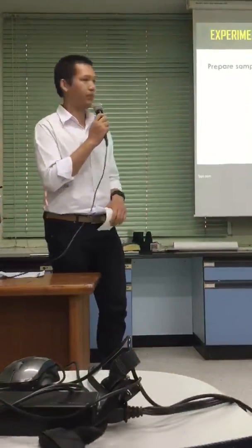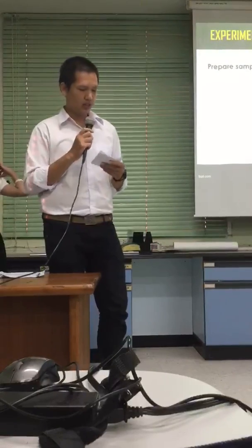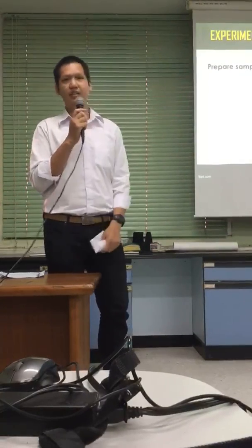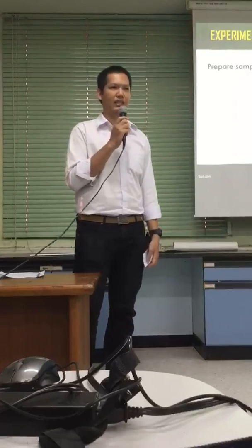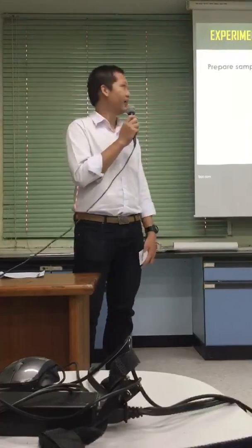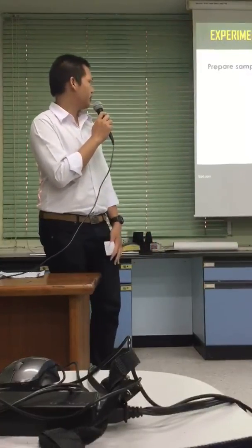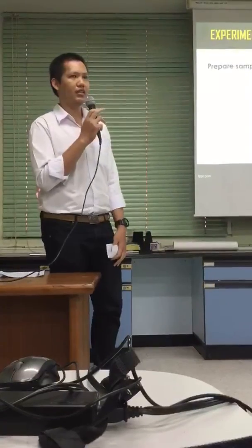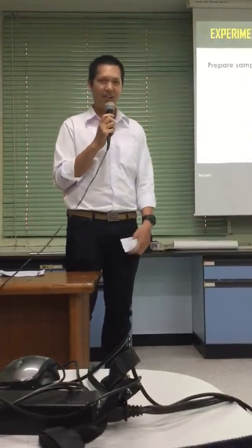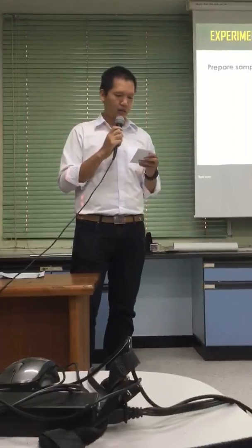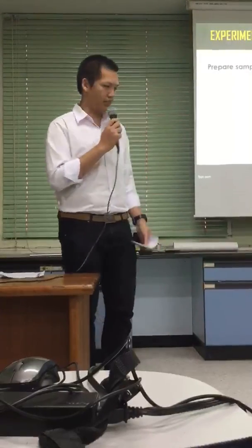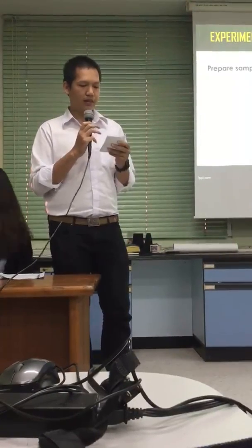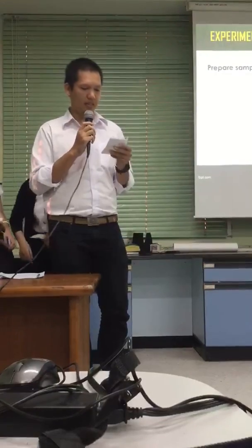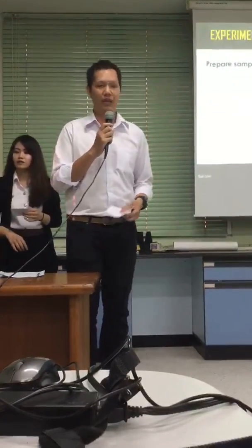In the experimental, we have two parts. The first part is preparation of sample. Then it is deposited on glass substrate by dip coating technique. Before the deposition, the substrate was cleaned by acetone, ethanol, and deionized water. Films were synthesized by sol-gel method. 2-methoxyethanol was used for solvent and diethanolamine was used for stabilizer.